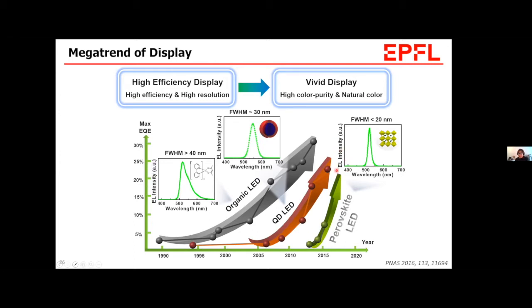And in addition, perovskites have advantages such as color tunability, and also what I already mentioned in the solar cell part, high charge carrier mobility, high defect tolerance, etc. The charge carriers do not have to go through very harsh condition where they end up combining non-radiatively, but the injected charge carriers can emit the light by a radiative recombination efficiently. So yeah, based on these advantages, perovskite LEDs have achieved efficiency over 20%. I mean, this is different from power conversion efficiency, but external quantum efficiency, in a very short term, less than several years, like perovskite solar cells.